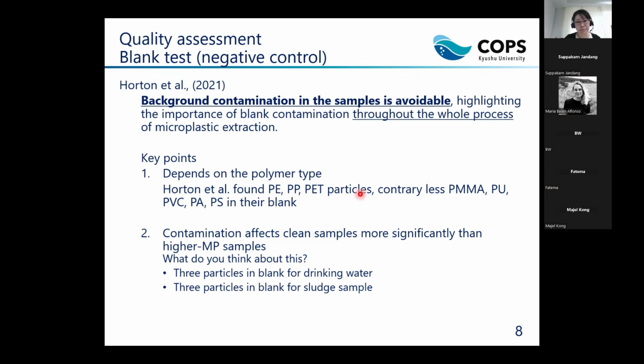But in contrast, PMMA, polyurethane, PVC, PA, and PS, they didn't find. So we need to consider the dependency on the polymer type. And the second point is that contamination level affects cleaner samples more than samples with higher microplastic levels.